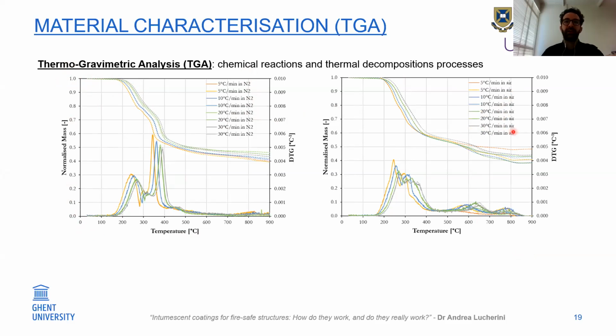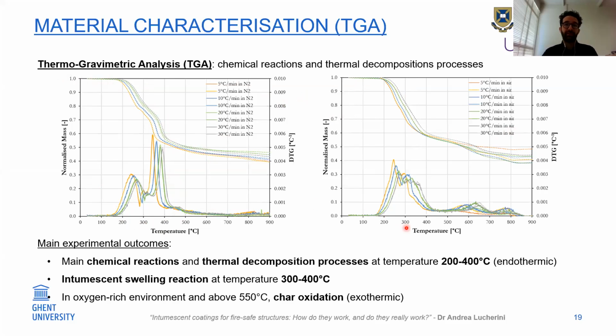So we had an oxidizing environment, sorry. You can see here the curves and how the coating mass decreases with different heating rates, and here in air with different heating rates. And if you take the derivative of this curve, you can see how the reactions happen at different temperatures. This is the difference between nitrogen and oxygen. What you can conclude from these experiments is, first of all, that you can characterize the chemical reactions and thermal decomposition processes using this experimental methodology. And the main outcome is that the main reactions and thermal decomposition processes happen at temperatures between 200 and 400 degrees.